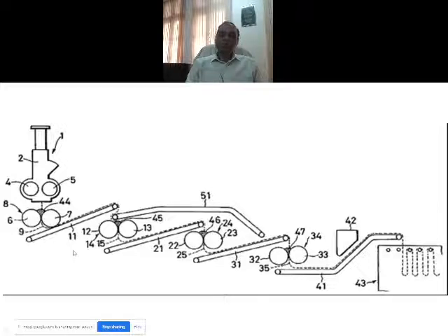So these are all the different layouts in a factory setup for treating a material that's coming from another batch operator called an internal mixer. We'll see that in a few minutes. But because we've been talking about the two-roll mill, the two-roll mill can be used for mixing. It is also used for refining, I mean final dispersion improvement of the batches mixed in an internal mixer. So the mechanism is to get a sheet refined here, here, here, and here. Finally, you get a sheet of desired width, and then it goes.